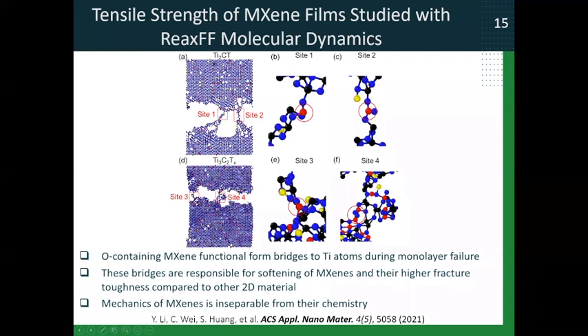between the edges of the growing crack, then what oxygen does, it basically connects one titanium atom on one side of the crack to another titanium atom on the other side of the crack. And in this way, it also maintains mechanical stability of this material. So this is another reason which may lead to softening behavior, but not abrupt failure as you would expect for graphene, for example, or other 2D materials which do not have these functional groups on the surface. So the presence of functional groups on MXene surface becomes important in mechanisms of failure of these materials. Okay, so this is another insight from modeling.